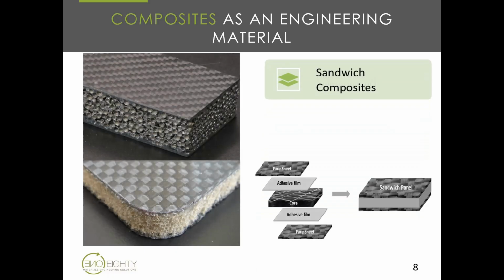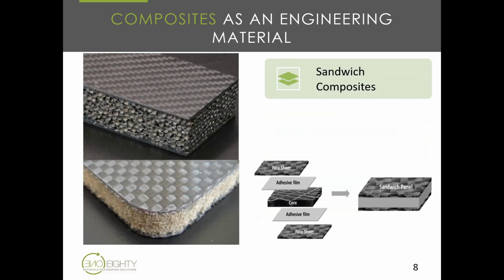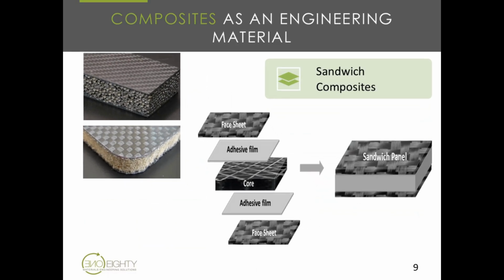Sandwich composites are quite interesting, and they're often used in the manufacturing of boat hulls or decks, so the structural frame of a boat. They can be built from either carbon fiber laminates or glass fiber laminates, but their build-up, as the name implies, is a sandwich between two laminates and a foam core on the inside. Typically for vessels, we've often seen glass fiber laminates being used for sandwich composites with a PVC core. What that helps with is that PVC is quite light and you'll get quite good buoyancy for the vessel from using that material.